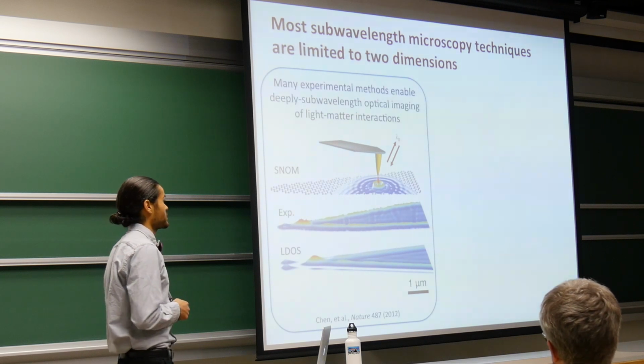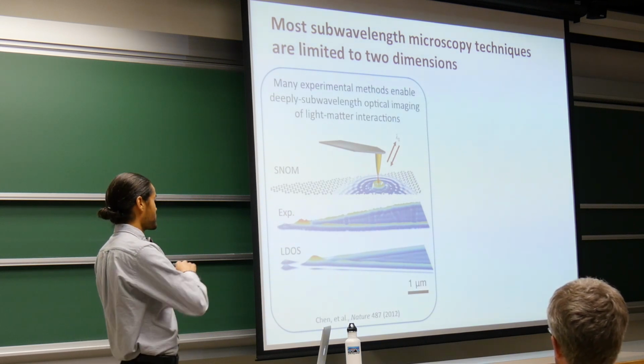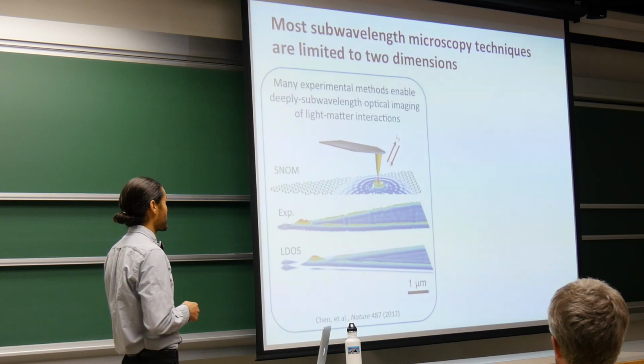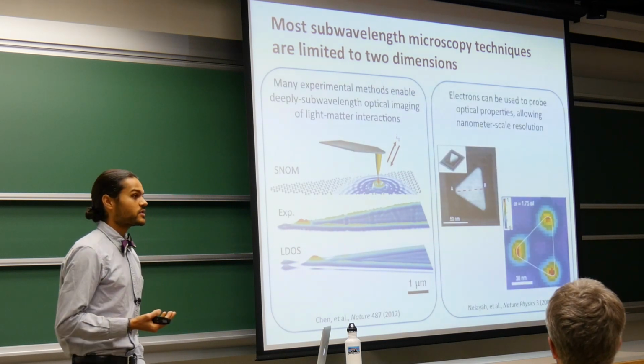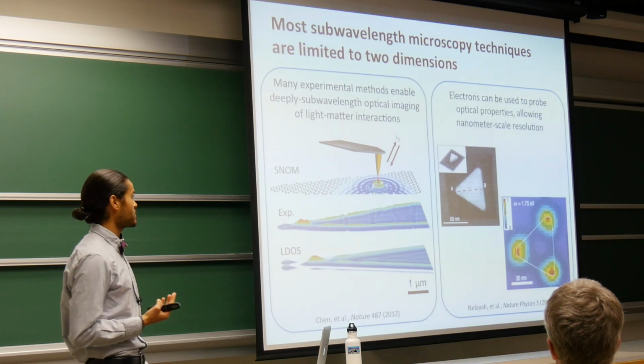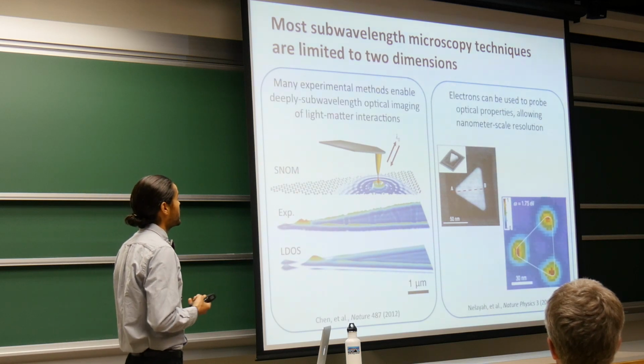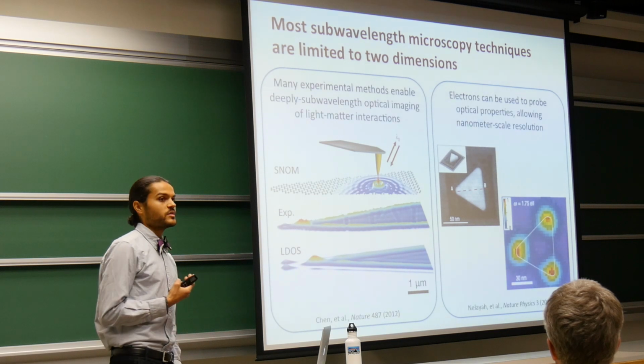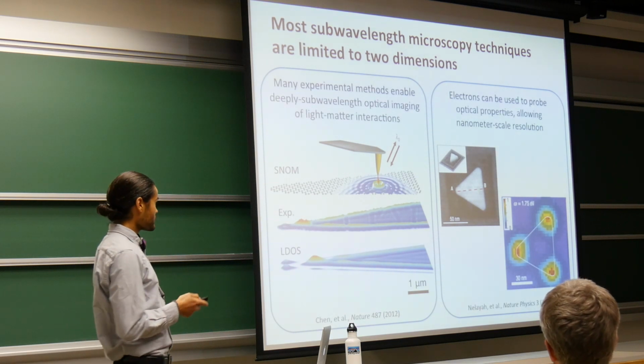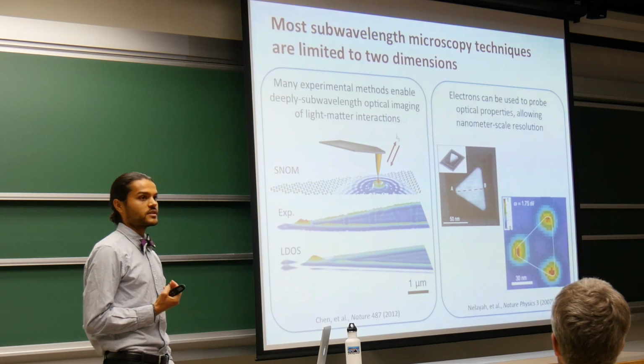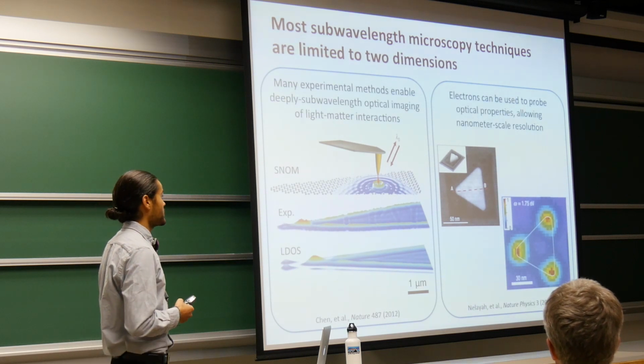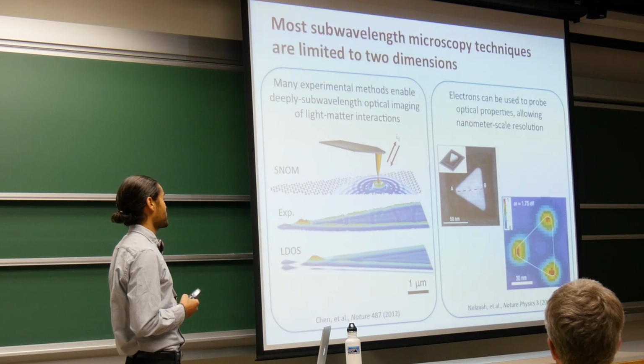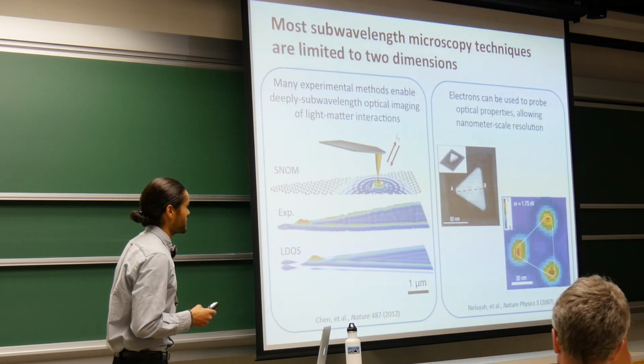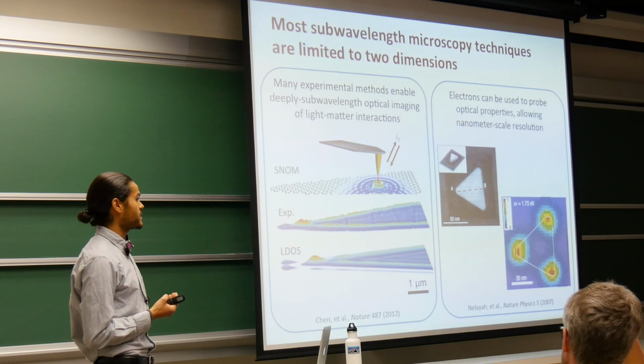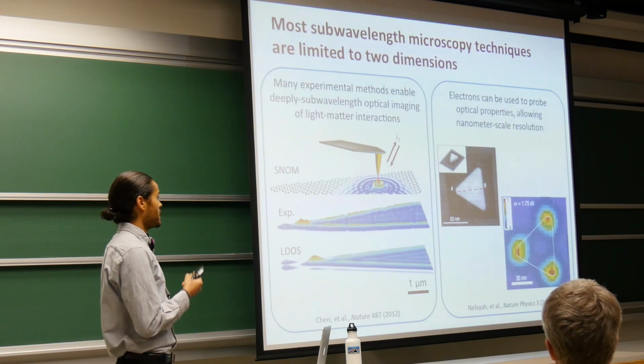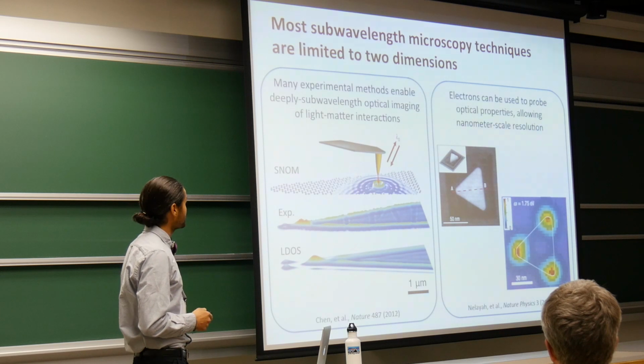In this case, they were able to correlate their experimental signal with the optical landscape right above the graphene sheet. Rather than relying on photons to achieve subwavelength imaging, we can also use electrons. And here we can see a silver prism imaged in a transmission electron microscope. In this case, the researchers used a technique called electron energy loss spectroscopy to study the optical properties of this particular nanoscale system, and that's what's shown on the bottom right. It's basically a map of the particular mode of this triangle at the energy given there.